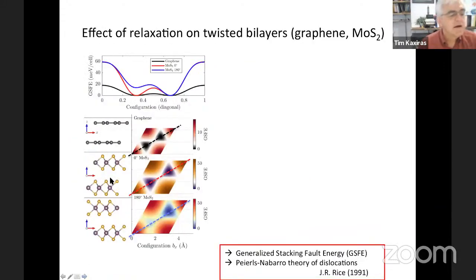Okay, so what I just described to you was based on interatomic effective potentials. This is an approximate description of the energetics between the interaction of the layers. But we can do a fully ab initio interaction of the different layers, and this is based now on density functional theory, the standard ab initio approach. And the way that we do this is by calculating what is known as the generalized stacking fault energy.